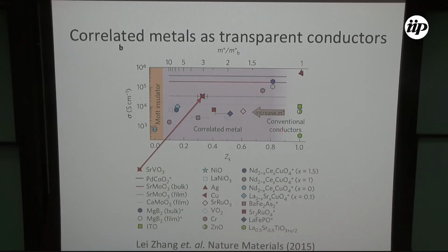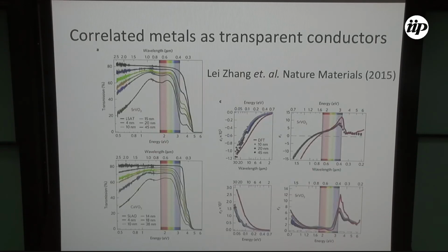So, yeah. It's not a problem of the free electron gas, and it's not a problem of the Mott insulator. It's intermediate strength of the correlations. But still, here you can see that the real part of the dielectric function has a nice Drude-like behavior, and the imaginary part is very small. It can be considered 0. And here, for the two materials, calcium vanadate and strontium vanadate, you see that they have a very high transmission coefficient of the order of 80%, depending on the width of the film. So they are really, they transmit light very well, and they would be very well suited to making devices.